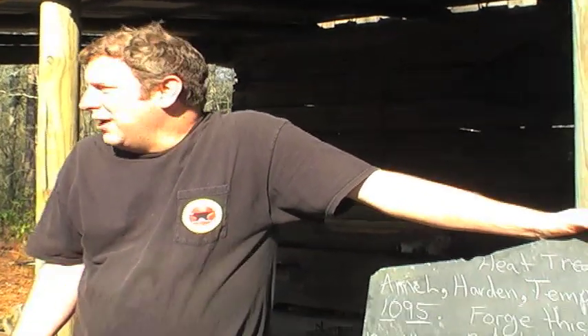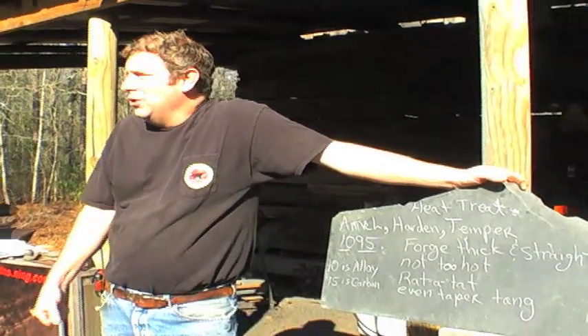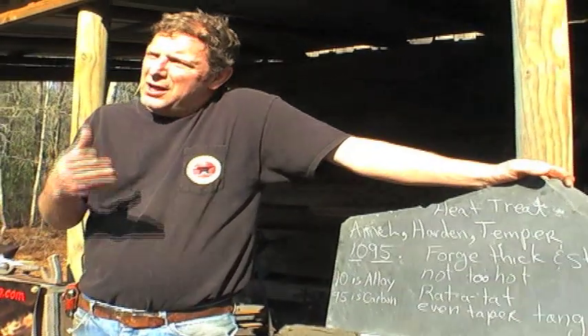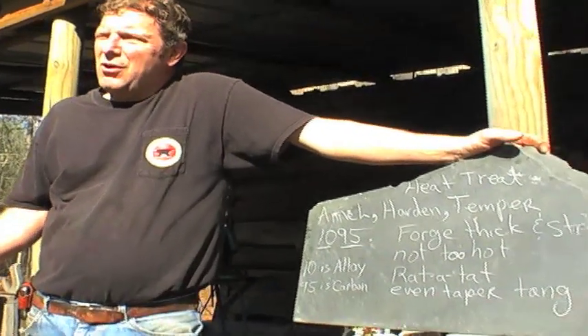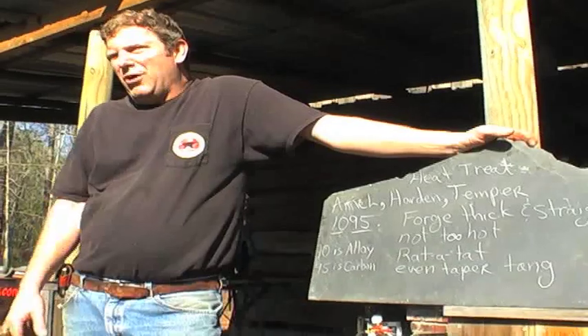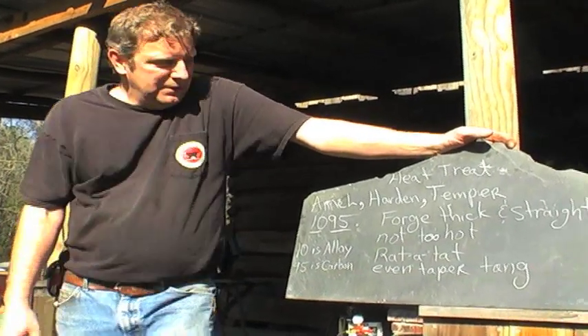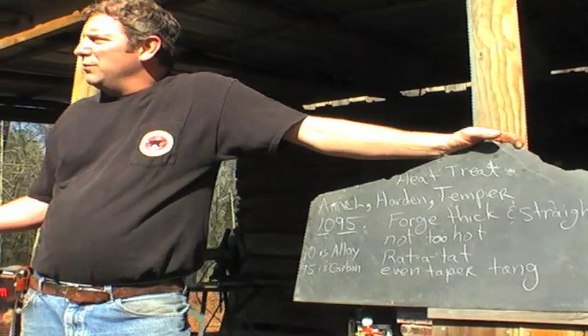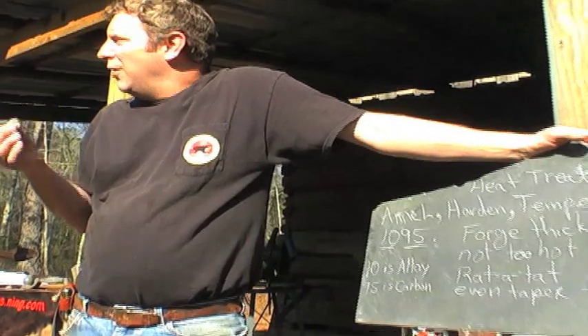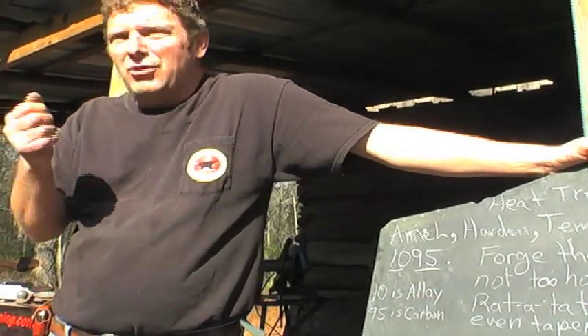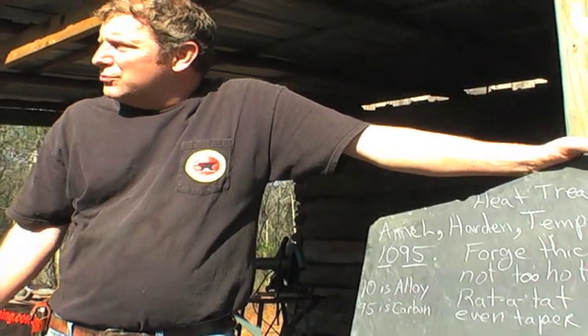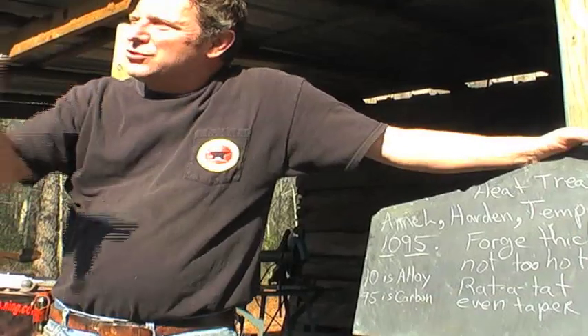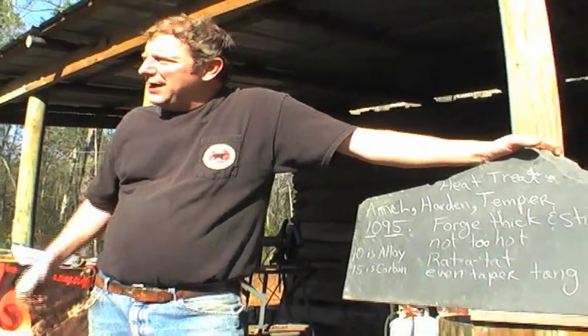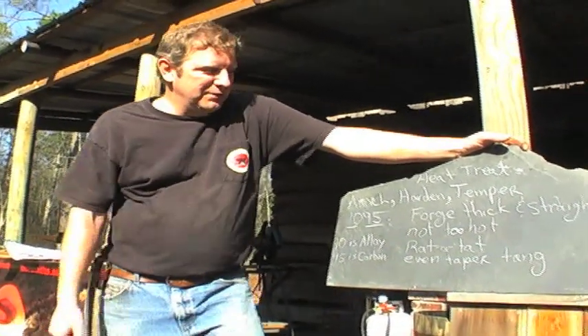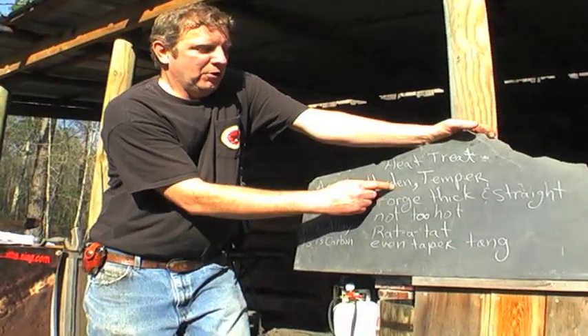So depending on your steel, it determines how long you keep it in the peanut oil. If you leave it in there too long, you can have trouble, and if you don't leave it in long enough, you're not going to get a hard temper. You want a Rockwell hardness, I believe it is, of 57, and you can check that with files. You can buy Rockwell hardness files for testing your Rockwell hardness. I don't have those files, but another way to check is to make sure your file will skate across it without actually cutting into the metal, and you know you're at the right hardness.